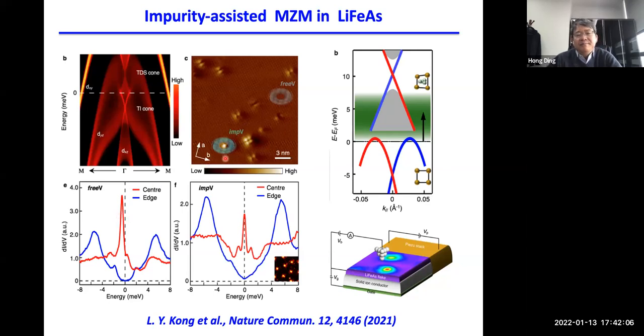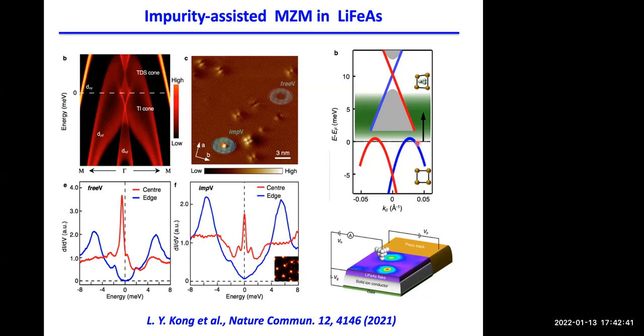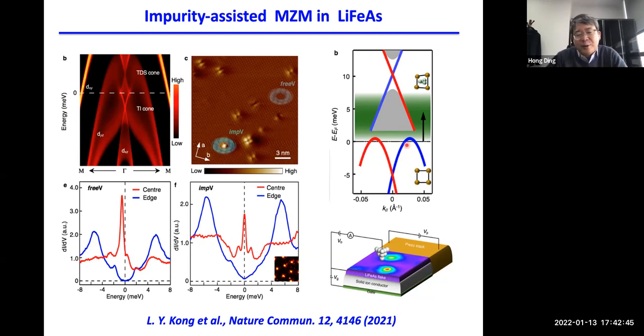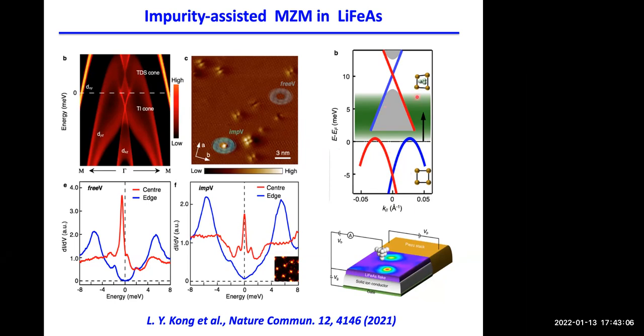But at some of the impurities, which are very often on the surface, we do see a zero peak. This is so-called impurity assisted. And we wondered what happened. So we propose that in this uniform superconductor, the chemical potential is sitting on this bending of the Dirac state, so you actually cross one branch of the Dirac state twice. In this case, you will have two Majorana zero modes in one vortex core, and they hybridize. So you don't see a zero mode, but if you have an impurity doping, you can shift, move away from this bending, and you can actually see a zero mode.